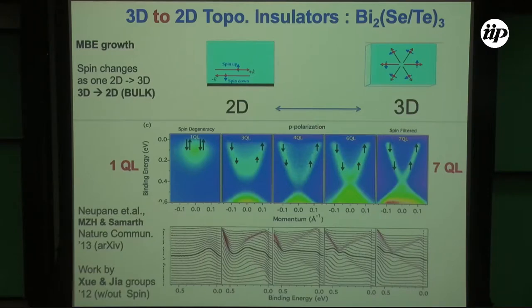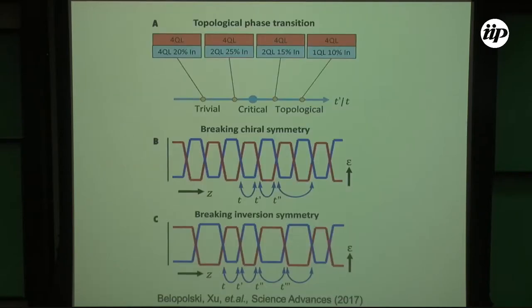So that way we know that we are entering a 2D limit. This is a 3D topological insulator, and on this side, this is a 2D film. It may or may not be topological, depends on certain things. But in some cases, it could be a 2D topological insulator. So this is our diagnostic, how we figure out the ideal thickness that maintains the Dirac cone. And if the Dirac cone is destroyed, we know the reason for that experimentally. Okay? Now you can see that the spin polarization here is smeared, unlike here, and there's a gap. So by looking at the top surface, we know that our film is too thin and we're looking at 2D states, not 3D.